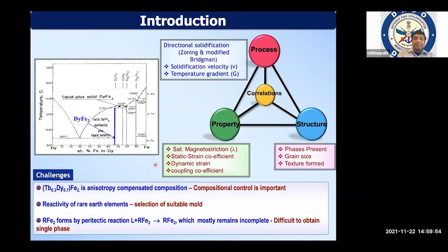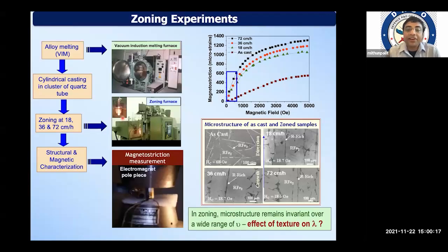Also this particular composition, as I was showing in this phase diagram, does not have any flexibility with respect to solid solubility. It has a kind of a line. So therefore, my composition selection should be very precise so that I don't end up with formation of other secondary phases which will deteriorate the property of the alloy. So in our place, we prepare this material in two different routes. One of the routes is called the zone melting route. This is one of the ways we are imparting the unidirectional solidification of the material.